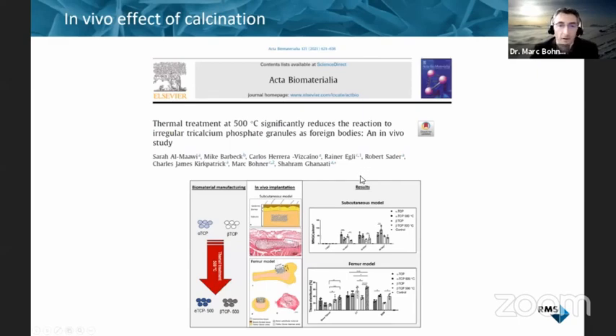And then, is it relevant in vivo? We have some ideas that it is, because we provided alpha and beta TCP granules to Shahram Ghanaati, who did then an ectopic and orthotopic implantation and looked at the biocompatibility reactions, the early reaction to these granules. The granules were either crushed, cleaned and delivered, or crushed, cleaned and calcined at 500 degrees for 24 hours to produce this calcium oxide layer. And there was a significant effect of this calcination treatment on the biocompatibility.